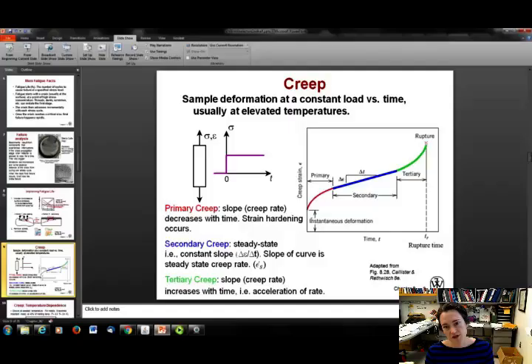And then the slope here, this instantaneous deformation, the slope will decrease with time until it reaches the steady state, which is the secondary part. They believe that this decrease in the slope with time of the strain on the part, which is called the creep strain, that decrease in the slope is due to strain hardening. So the part, the metal, is actually getting tougher in service. Then it reaches a plateau where the strain hardening is actually battling with the recovery phase for the part, because remember the part is being subjected to heat. And then you have what looks pretty much like a flat, straight slope there, okay? And then that stage is called secondary creep.